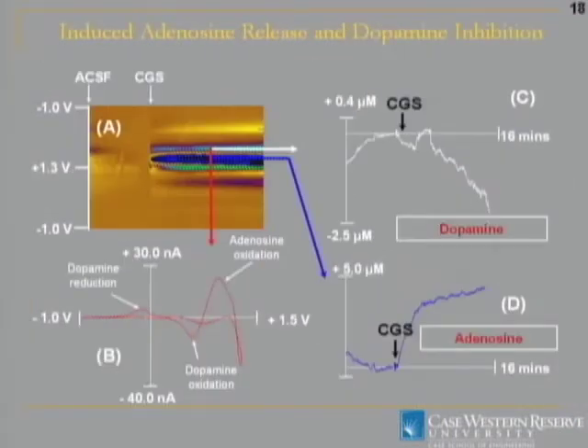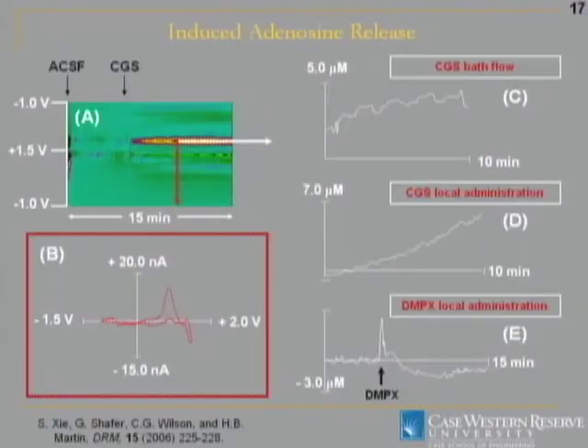Dopamine oxidizes at a lower potential, so it's not going to interfere with adenosine measurement. Before you leave that, could you back up there? I don't understand that scale on the upper left panel, minus 1 volt. Oh, this? Each one of these vertical lines is a complete voltammetry sweep. So I've started at -1 and gone up to 1.5 and back down to -1. So I've completely done the full scan in both directions. So it's not just in one direction.